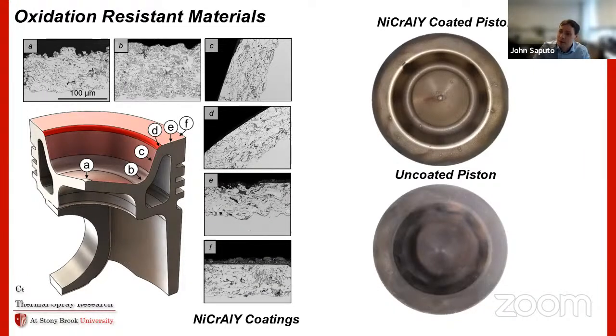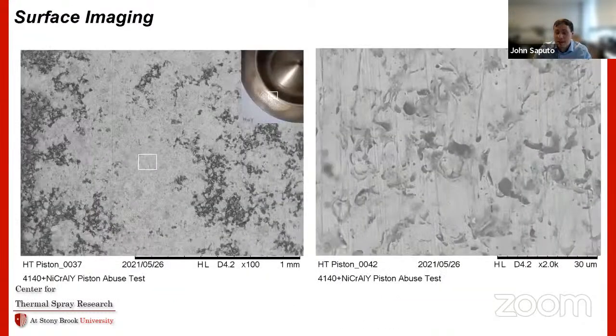You can see where the air and fuel combust on the surface and those little periodic arrangements around it in a circle. And you can look at cross-sectional micrographs of this after testing here on the left, and you don't really see any degradation to the system. It's after 50 hours of testing at 519 C. And you do some surface imaging of this.